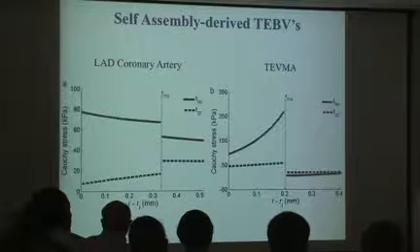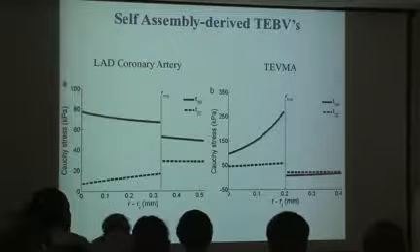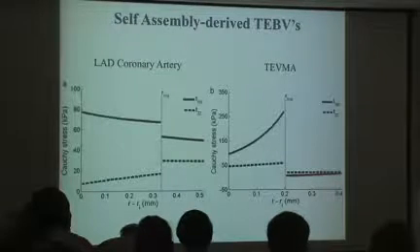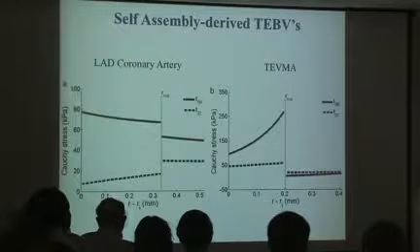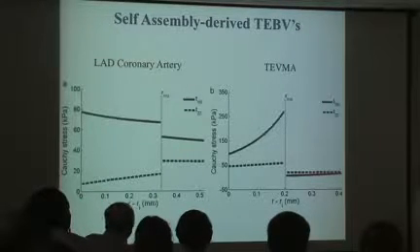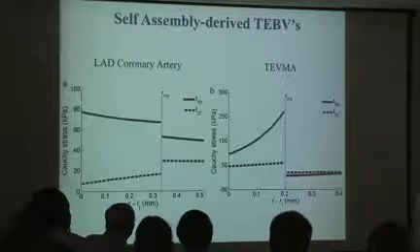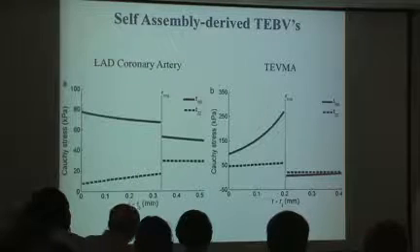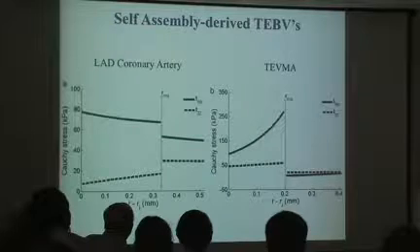It gets less compliant, right? It gets stiffer. And so even though we start out with a vessel that has the right compliance, has the right geometry, if it doesn't have the right mechanical properties or it doesn't have the right stresses in vivo, it can induce maladaptive remodeling. And this can cause a diverging path for this thing to become stiffer and stiffer, compliance mismatch, and then the vessel fails or occludes or something.